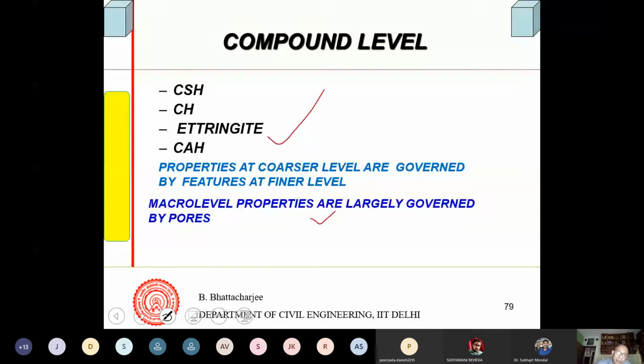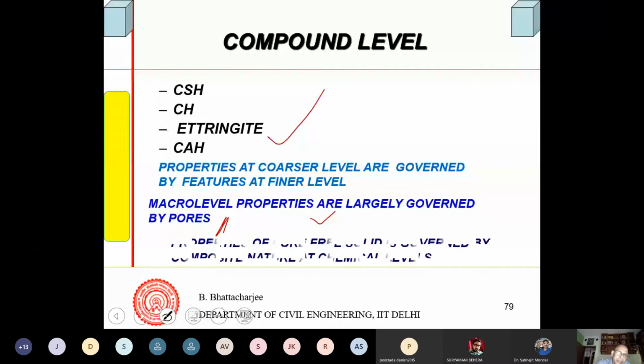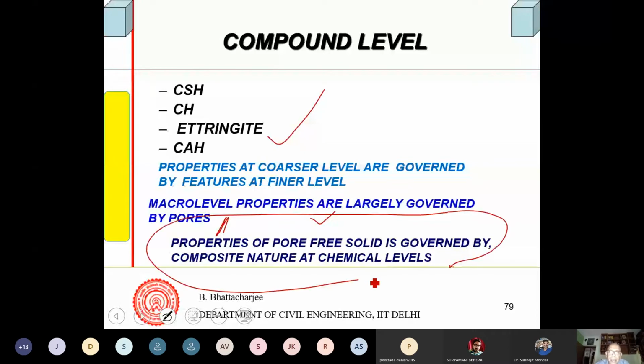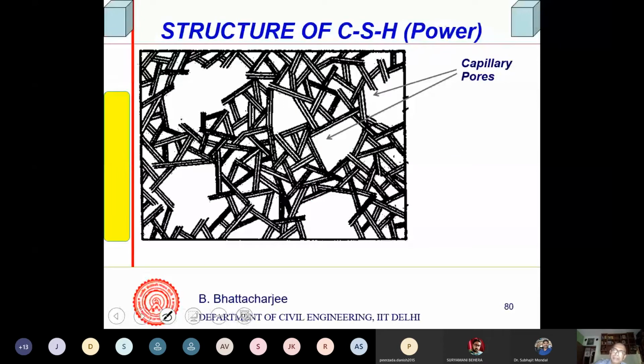Macro level properties are governed by the pores. There are a lot of pores in the system, we shall see, and performance of the pore-free solid is governed by this chemistry. This is the probable structure of cement paste given by T.C. Powers. Capillary pores, these are called large pores, and there are finer pores inside called gel pores. And hydrated cements are layered structures. C-S-H gel structure, they are gelatinous material.